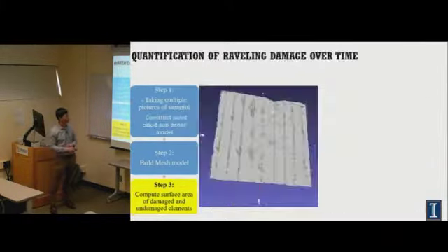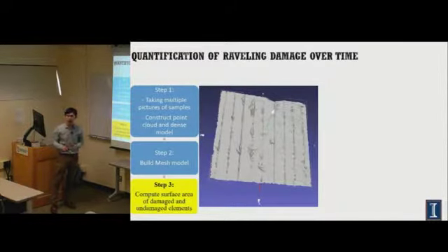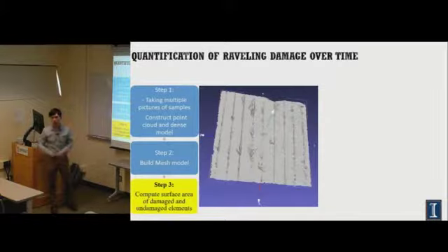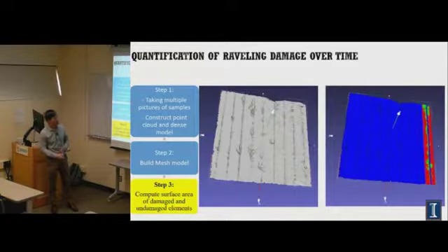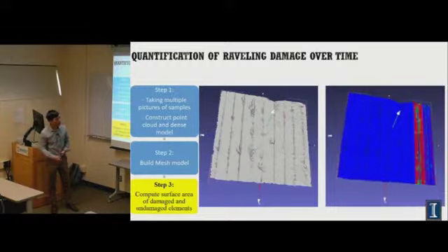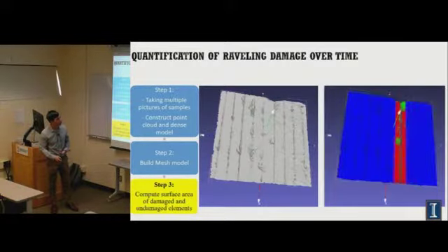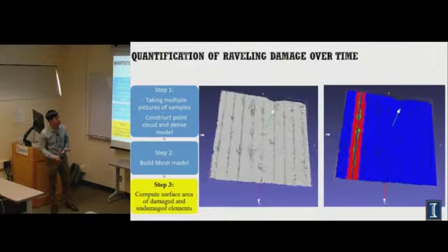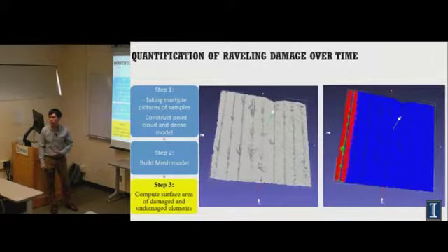Based on that, I will measure the damage of each cut that I make in the whole block of concrete, like every 30 minutes interval. What I see here is, firstly, we have small raveling, but then it will increase, and then decrease, right?